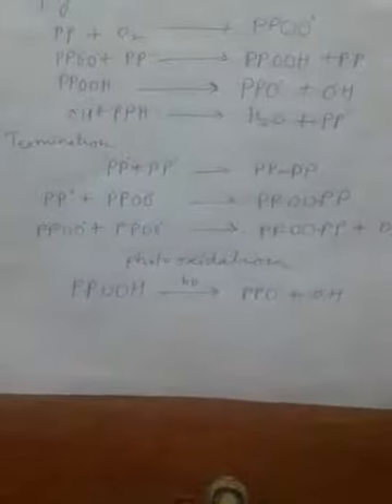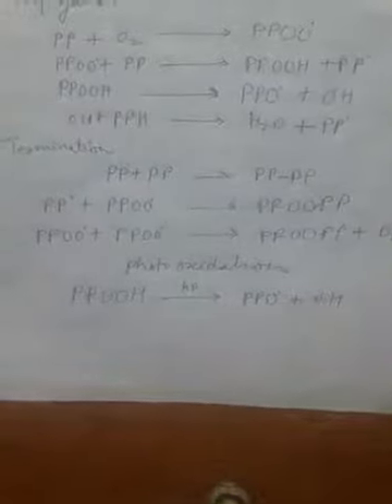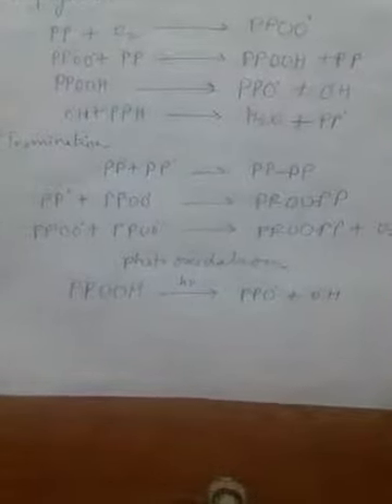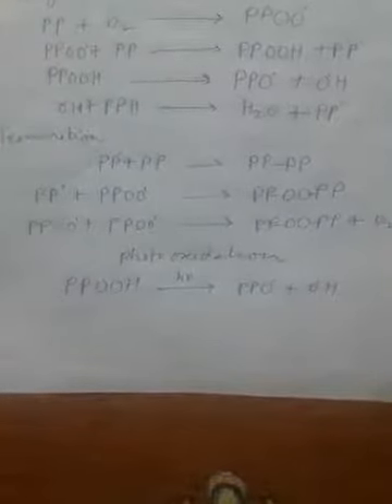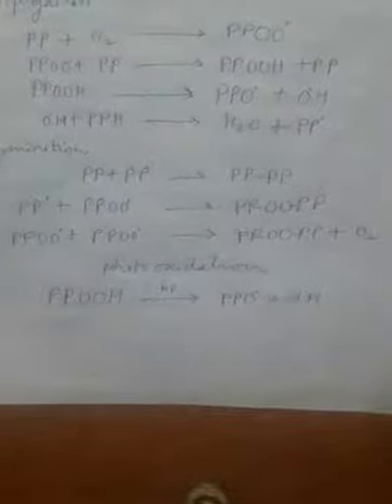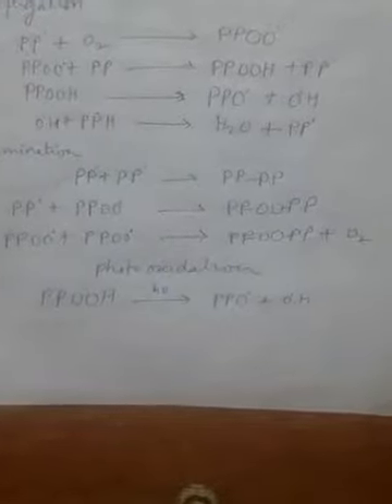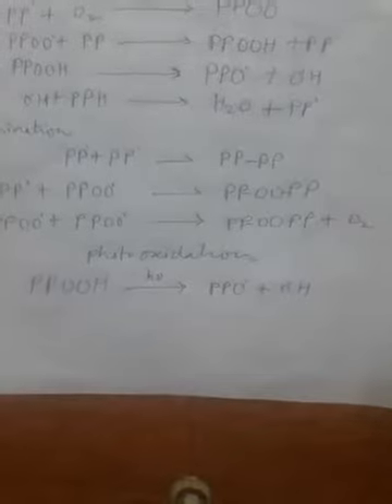which is much faster. The termination of the reaction may result when PP dot and PP dot, two radicals from different molecules, combine together, and termination takes place with big molecules. You can see the size of the polypropylene molecule after degradation is unpredictable. So processing such polypropylene material is difficult, because during melt extrusion and melt processing the viscosity may be affected. So this is overall the thermo-oxidative degradation.